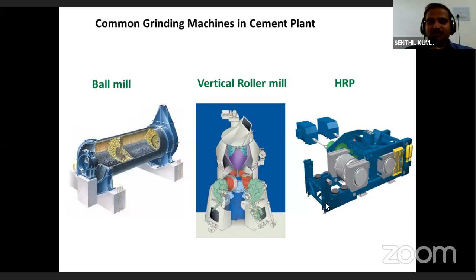Yes, it's a good question, of course. When we talk about wear and tear, it is common in all these three machineries. For example, in ball mills, the wear materials are the grinding media and the liners. If I put a 90 mm media inside the mill, after some time it will reduce to 80 mm media. Then the 80 mm media will become 70 mm, 70 becomes 60, 60 becomes 50. The 50 will not perform, and then the 90 has to do the impact job.